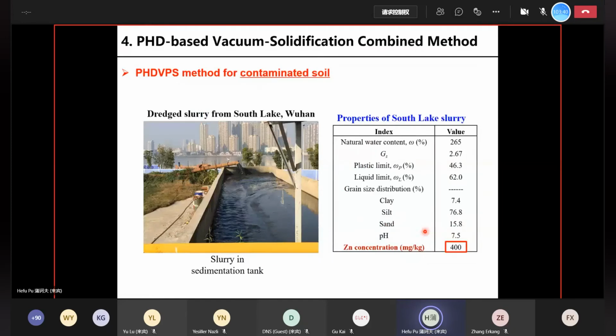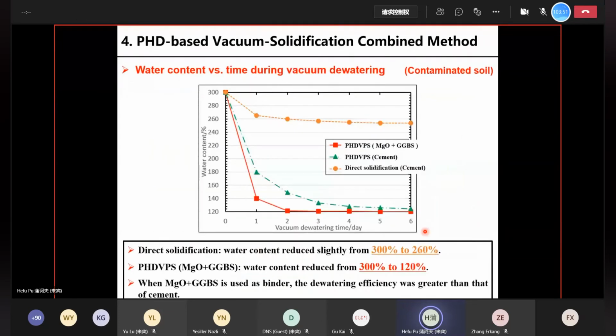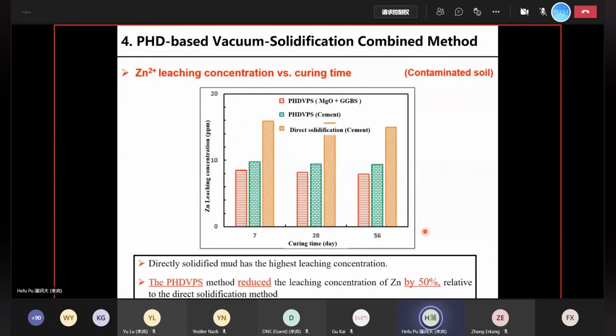So in addition to the clean mud, we also look at the contaminated mud to look at the stabilization effect. I will go quickly here. So here, this is the leaching concentration of heavy metal zinc, and you can see that the direct solidification has the highest leaching concentration. And then when we use the PHDVPS method, that can reduce the zinc concentration by about 50%. So a significant increase in the stabilization effect.